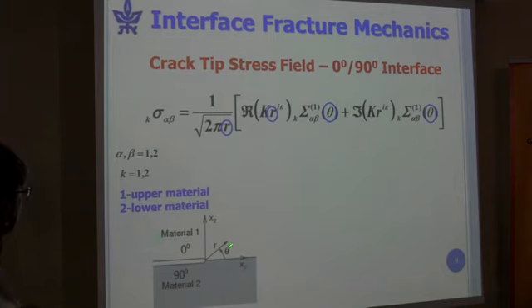And so what it does is, as the stresses go up to infinity, 1 over the square root of r, they start to oscillate very rapidly. And as long as that's relegated to a very small zone, we can use these ideas. One has to examine that, and as long as that occurs, we're okay.